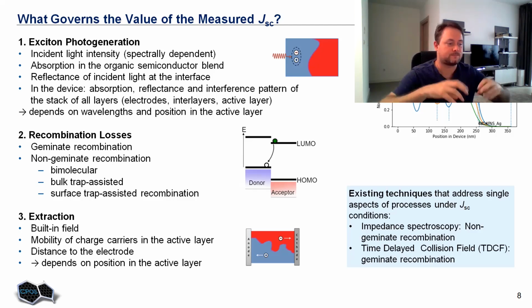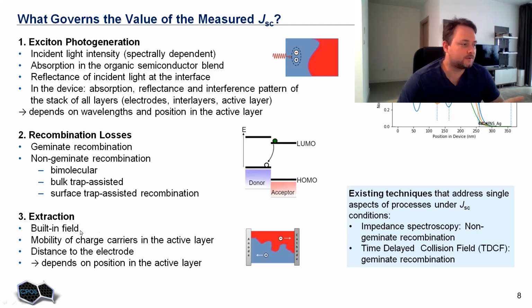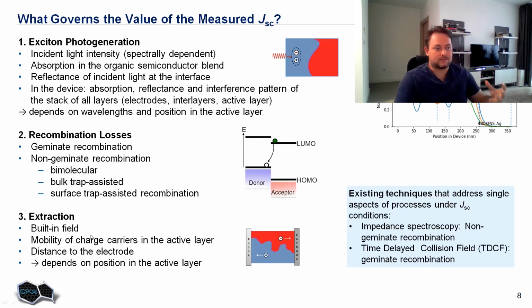So once we have already formed these free electrons and holes, they start to travel via respective networks in this bulk heterojunction toward electrodes. They can recombine. So it could be bimolecular, band-to-band recombination, bulk trap-assisted recombination, and also surface trap-assisted recombination. So we lose charge carriers while they are moving in the active layer. Another important parameter is extraction. So we care about the built-in field, how strong the field is inside the active layer to separate these charge carriers, and their mobility, because if we have high mobility of charge carriers, they can swiftly be extracted from the active layer and contribute towards the useful current, which we want. However, there is always a compromise between all these parameters, and we need to deal with that.